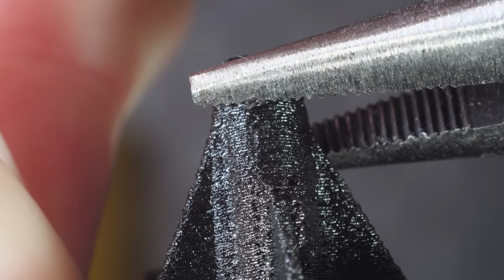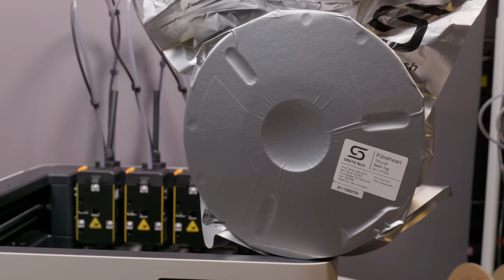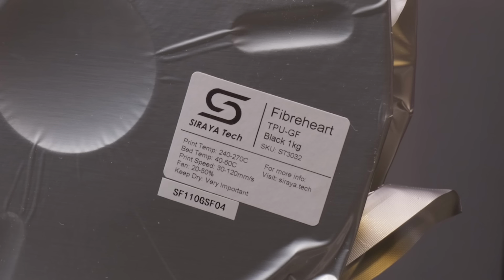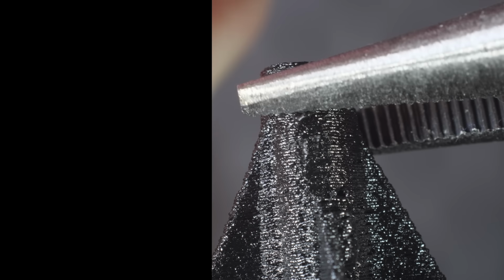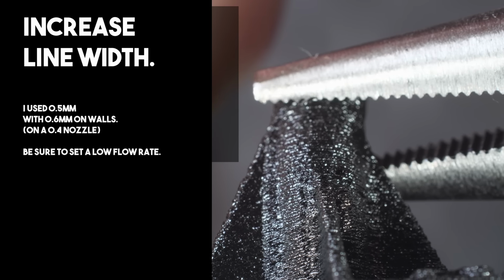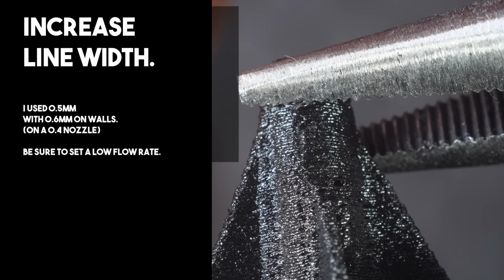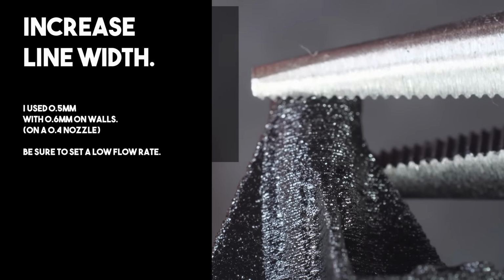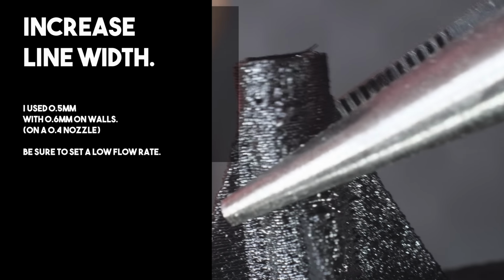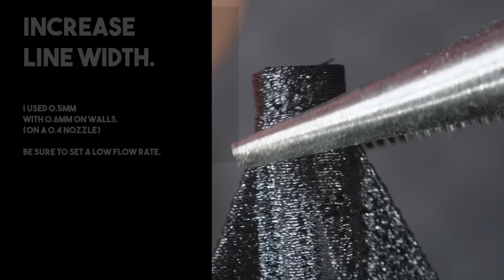Don't exceed the top end temperature of 270 degrees C because it's a hard safety limit. You do not want to overheat TPU. It's dangerous, in fact, but do increase the line width. I did find that just increasing the line width made a huge difference on its own. So that does kind of make a case for 0.6 nozzles, I suppose, doesn't it? If you do have a need to increase the layer bonding, I think the better thing is to design around it rather than trying to tackle it head on.